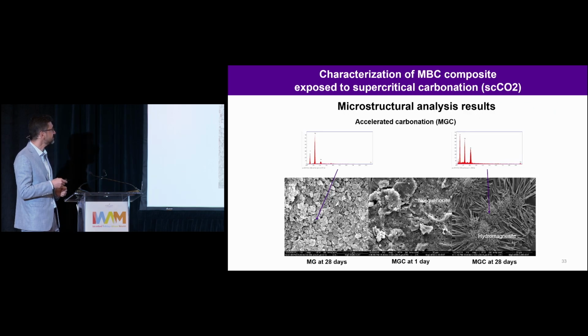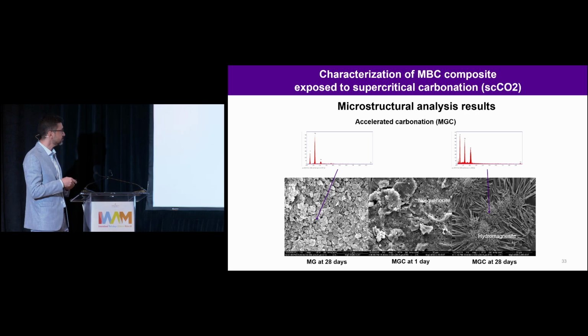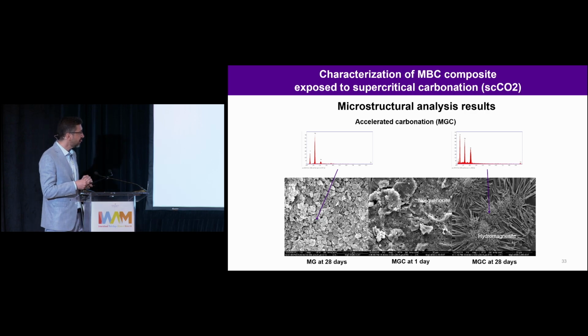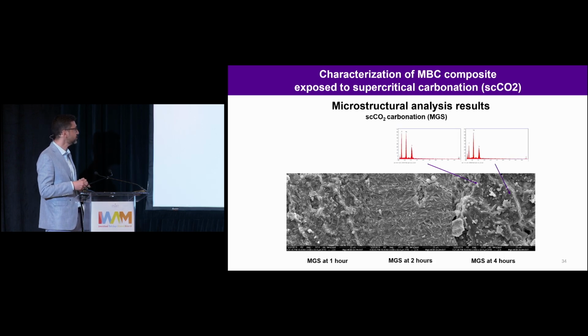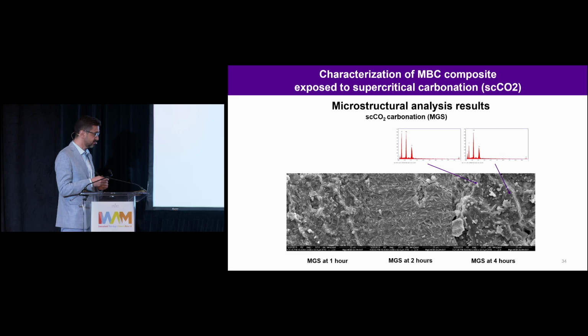And we also observe this in SEM. Here we see magnesium cement cured in the air condition. Mostly we see the flake-type magnesium hydroxide. There is not much carbonation, but if we accelerate the carbonation in the curing chamber, nesquehonite and hydromagnesite phases appear. For the supercritical CO2, just after 1 hour, 2 hours, and 4 hours, we see the needle-like shapes, which are the nesquehonite phases, and then after 4 hours, all these nesquehonite phases are kind of fused, and there is no clear pattern of the crystals or minerals.